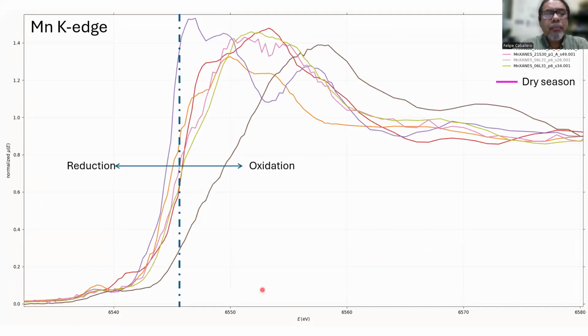In the case of manganese, the pink trace shown here in the middle of the other traces is that observed in the dry seasons. All the manganese in the dry seasons behaves the same, but as you can observe, there are several forms of manganese. This vertical line indicates the absorption edge of manganese, the K edge, and the more to the left the edge is, the more reduced the manganese is, and the more to the right the edge is, the more oxidized it is. So we can see here that we have a lot of different species of manganese during the rainy season.